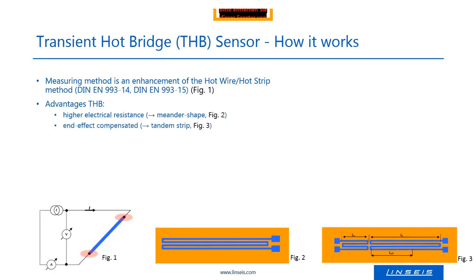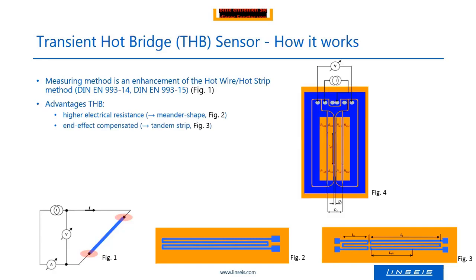And then the next step is not to use only one wire, but four wires in one sensor. We have two wires on the outer parts of the sensor and two in the middle. Why are we doing that? The answer is, if only one wire is used, then before every measurement, the zero voltage of that wire needs to be measured and subtracted from the measurement. And the zero voltage is changing with the surrounding conditions, with the surrounding temperature, humidity, and so on.